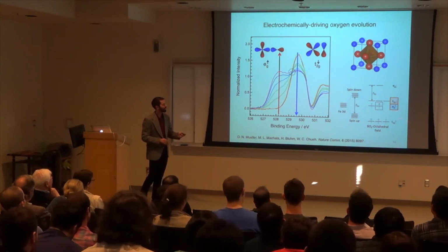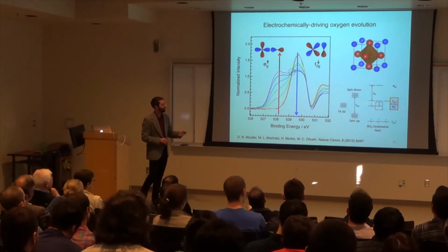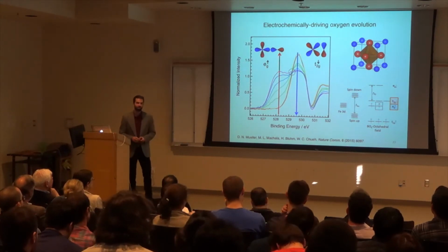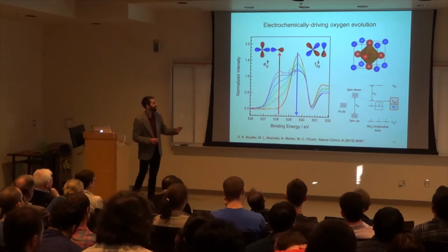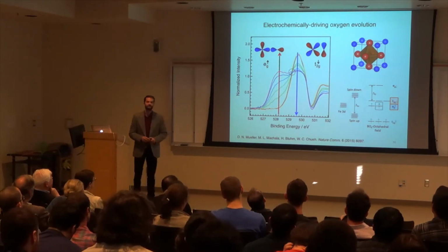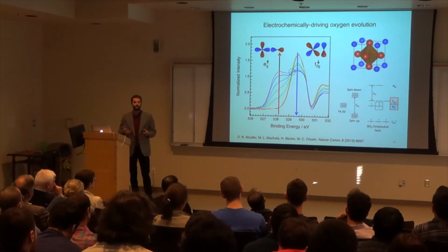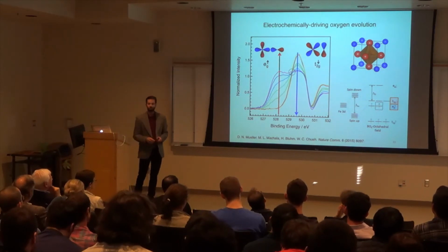Okay? Now, for those of you familiar with crystal field theory, this is the eg up state and this is the t2g down state. And so what we're doing here is we're basically filling and unfilling the eg up state, the high spin state. And this change here on the t2g down state is really just a change in the covalency of the transition metal oxygen bond.